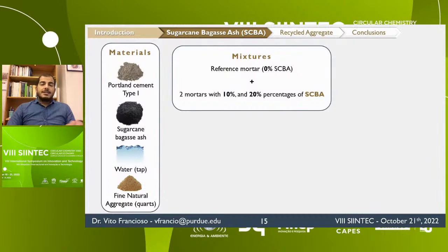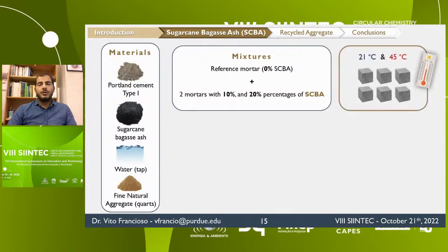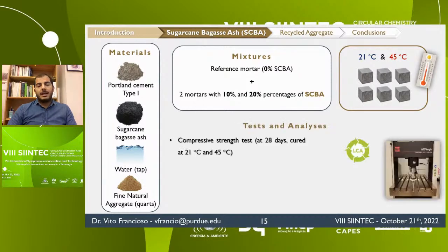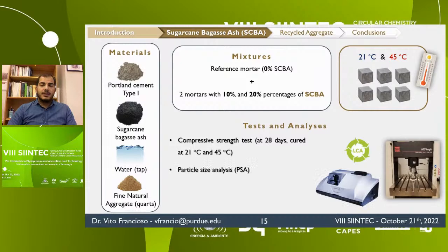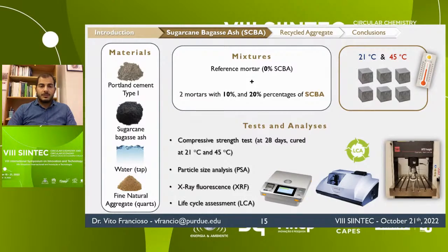For these studies, I designed 3 mixtures: a reference mixture without sugarcane bagasse ash, and 2 mortars with 10 and 20% replacement of cement with sugarcane bagasse ash. These replacement percentages were based on previous research, while the curing temperatures chosen were 21 degrees Celsius and 45 degrees Celsius. For the experimental campaign, I performed compressive strength tests, physical and chemical characterization of the ashes, and finally, a life cycle assessment.